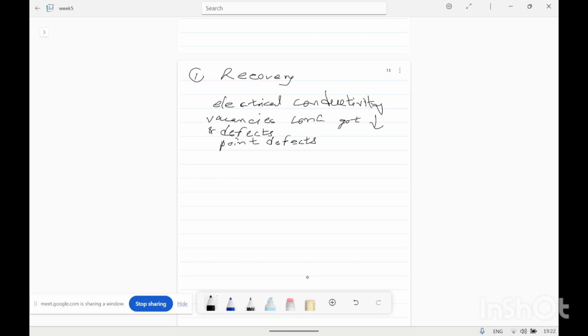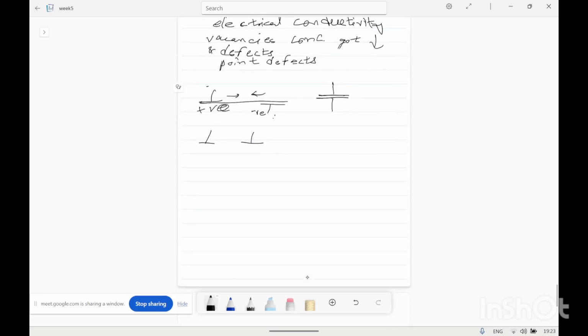Second is the annihilation of dislocations. On a plane, if one dislocation is of positive sign and the second dislocation is of negative sign, if they come to each other, then they will annihilate. This represents the extra half plane at the top, and this represents the extra half plane at the bottom of the slip plane. After coming to each other, they form a single long-range plane, annihilating the dislocation by formation of a new plane. If dislocations are of the same sign, they repel each other. Only opposite sign dislocations can annihilate.